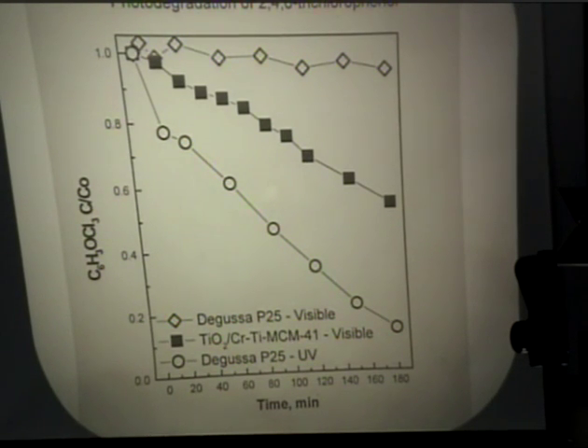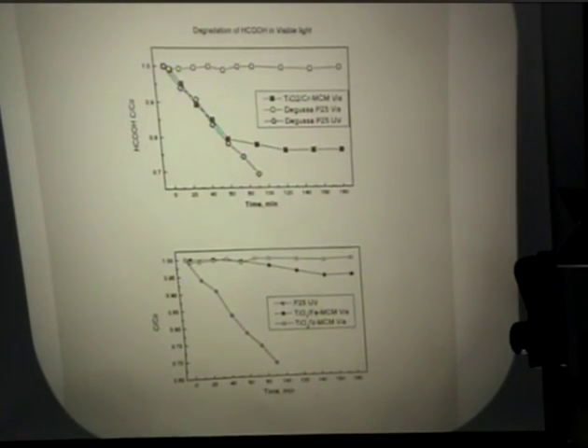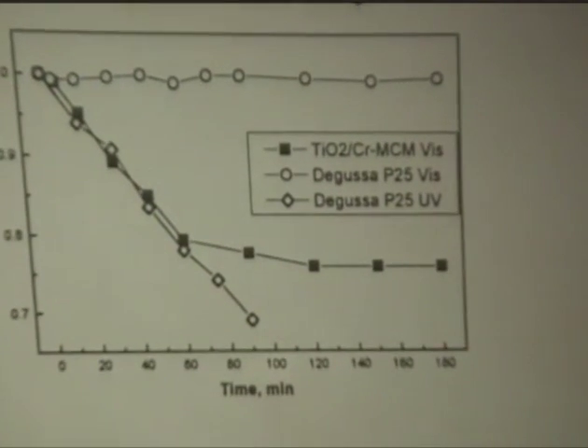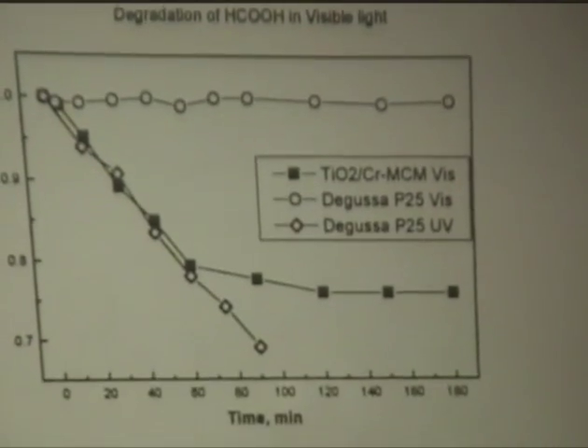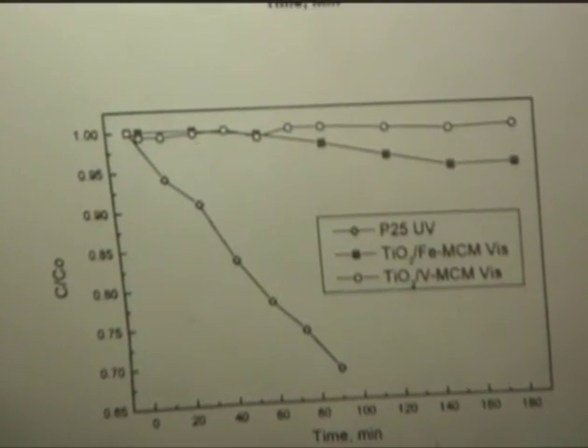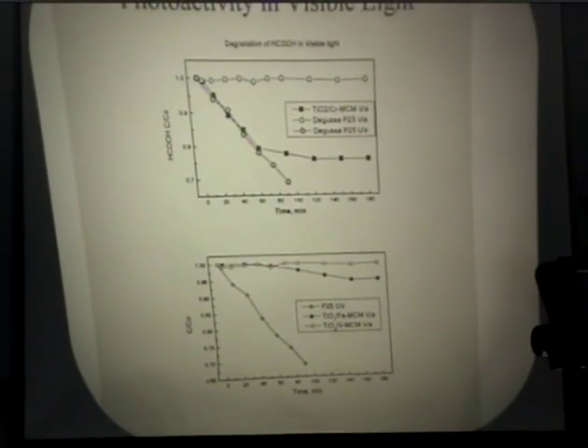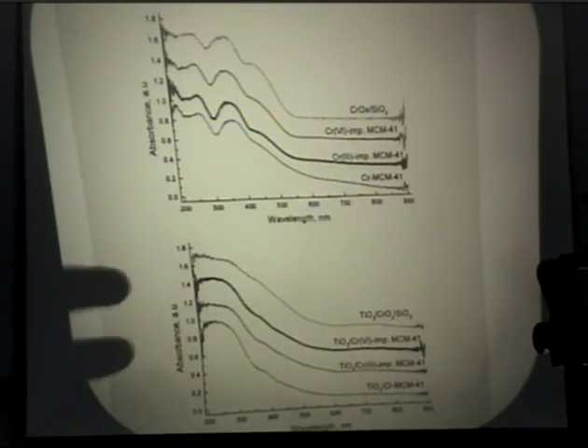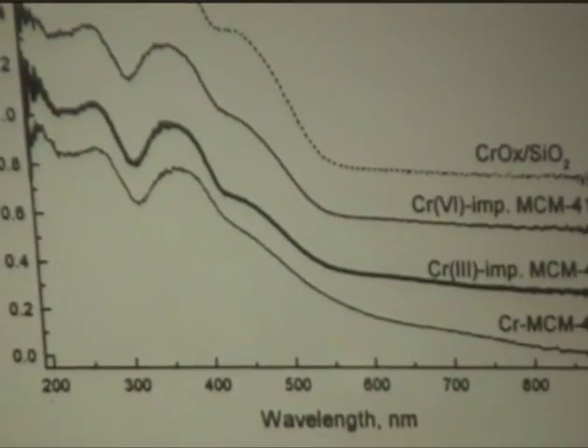If we put more chlorine on the probe molecule, we also observe sustained reaction for a long time. Although this graph shows 180 minutes, we ran for 6 to 9 hours and did not observe deactivation. So titanium-loaded chromium-MCM catalyst proved to be active.